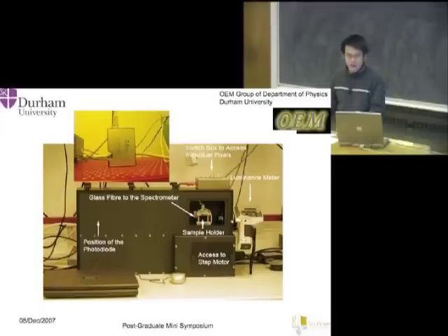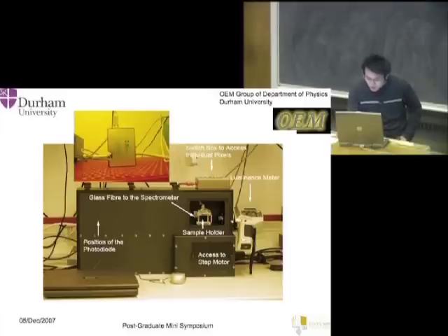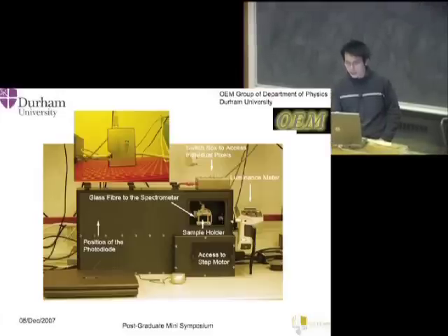And this is what we use to measure our samples. We put our sample in this holder. This is the luminance meter, and inside this box is a photodiode. Inside here is an Ocean Optics USB2000 spectrometer. This box is the switcher to control which pixel lights up. And here is a motor, so we can rotate the sample. The reason we need a photodiode and a luminance meter is to calibrate our data. We record data from the photodiode, rotate 180 degrees to measure the brightness, and then calibrate it.